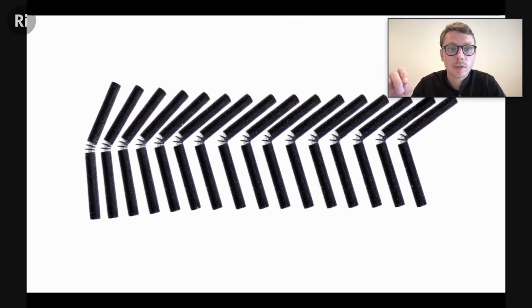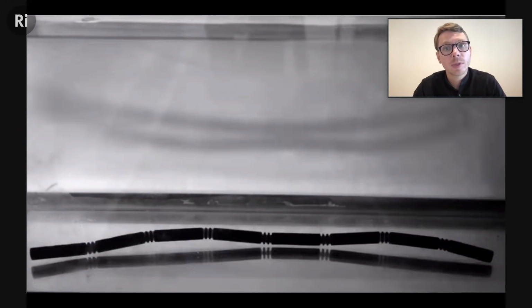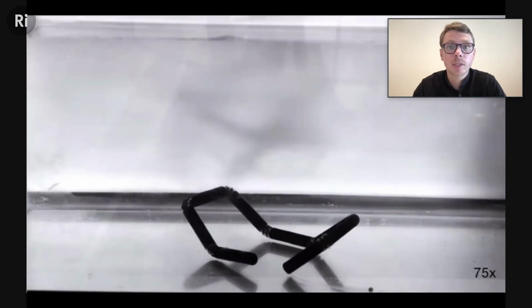With different materials, they can be activated by different activation energy. So what you're seeing here in the joint, the clearish material is a hydrogel. So we deposit just the right amount of hydrogel in the right geometries so that when it's activated by moisture, it transforms from one shape to another shape. And so then we started printing all sorts of things and dipping them underwater.